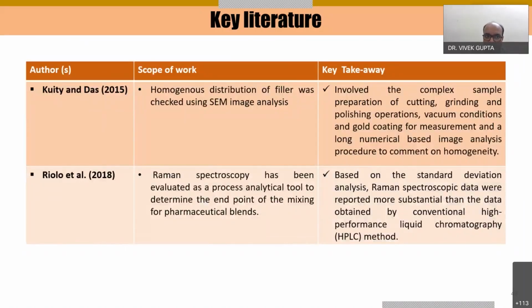And these are some of the key literature, like Kuity and Das in 2015. They worked on the homogeneous distribution of filler, and they checked it using SEM image analysis. It involves complex sample preparation, cutting, grinding, polishing operations, vacuum conditions and gold coating for measurement, and a long numerical image analysis procedure to comment on the homogeneity that is required in that particular case.